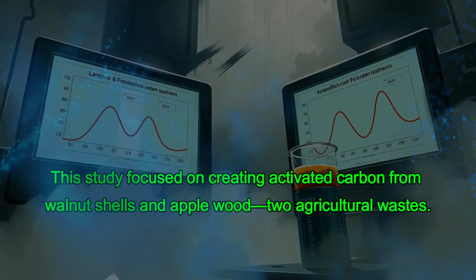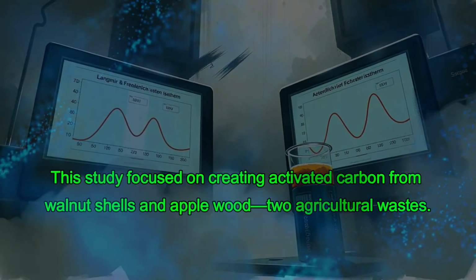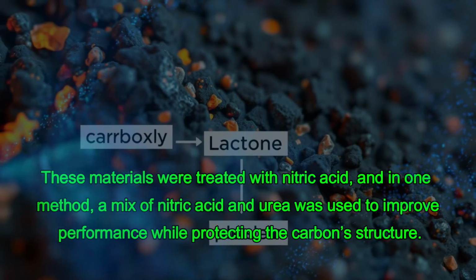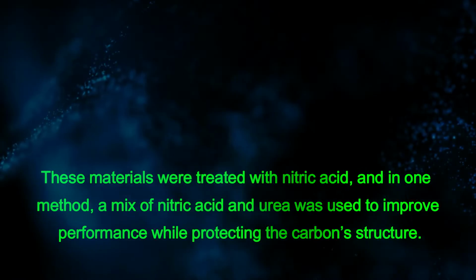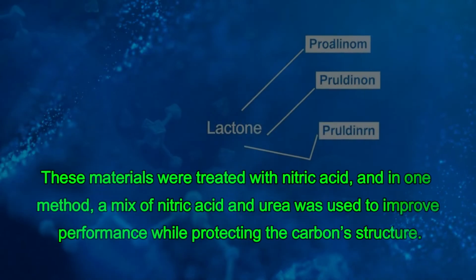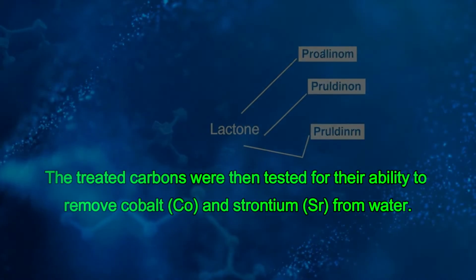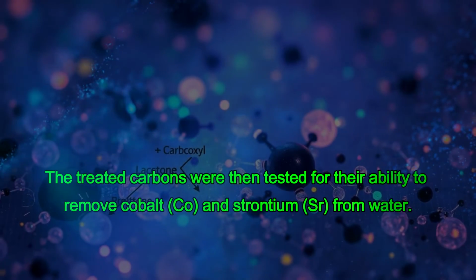This study focused on creating activated carbon from walnut shells and applewood, two agricultural wastes. These materials were treated with nitric acid, and in one method, a mix of nitric acid and urea was used to improve performance while protecting the carbon structure. The treated carbons were then tested for their ability to remove cobalt, Co, and strontium, Sr, from water.